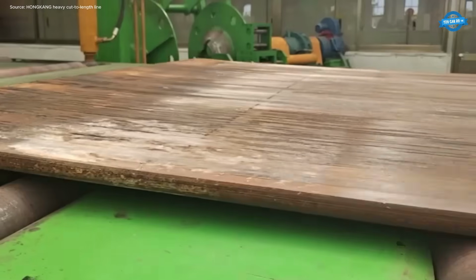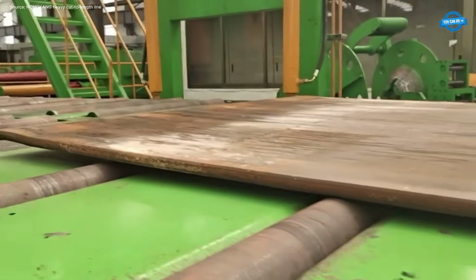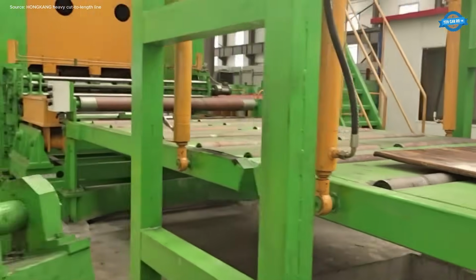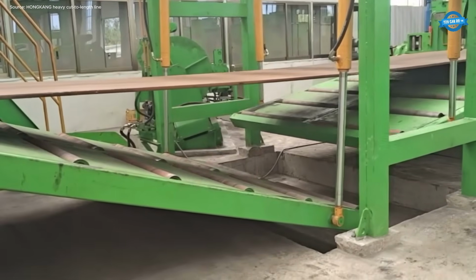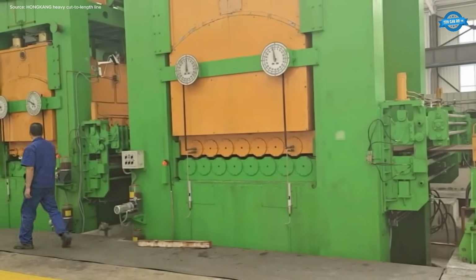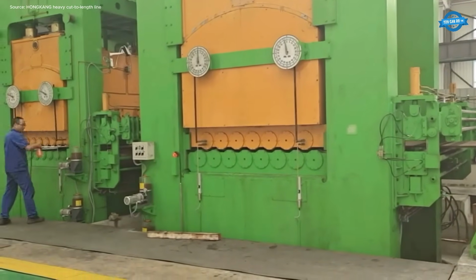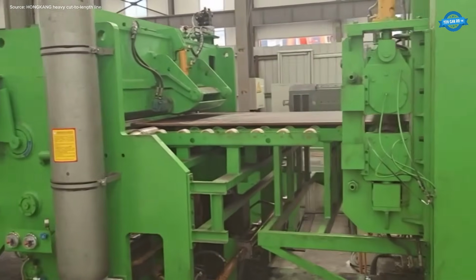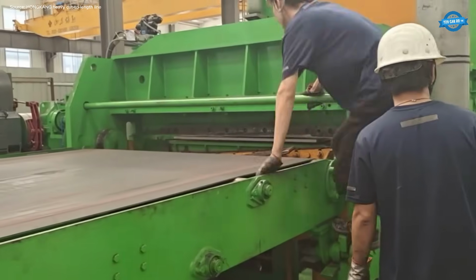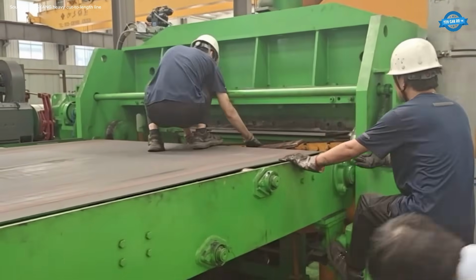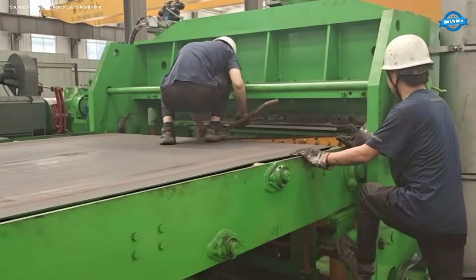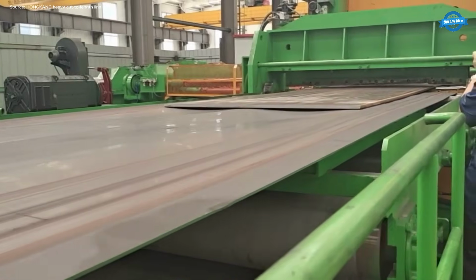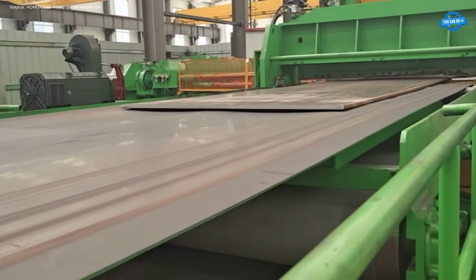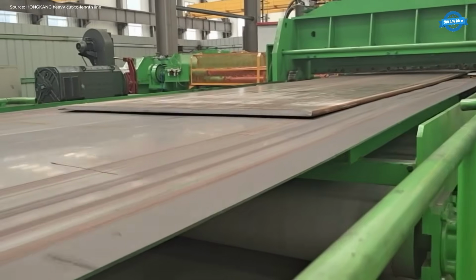Once leveled, the strip enters a measuring system, typically using an encoder wheel or laser gauge to control the length of each plate to exact specifications. The material is then fed into a hydraulic or mechanical shear, where high-force blades execute a clean cut through the 25 mm thick steel. Depending on the production rate and plate length, the system may operate in a start-stop or flying shear mode to maintain efficiency.